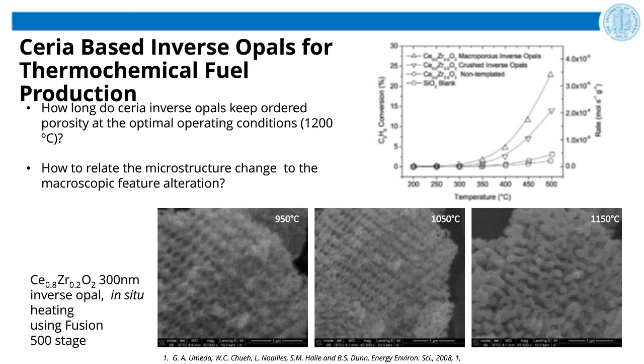The objective of this project was to predict and quantify the high temperature behavior of ceria zirconia inverse opal for use in thermochemical hydrogen production. Particular interest was in how the material degrades at high temperature. Using the in situ SEM setting with the prototype heating stage, we were able to directly monitor the degradation of the structure at high temperature and also find an empirical relationship between the grain size of ceria and the window size of the inverse opal.